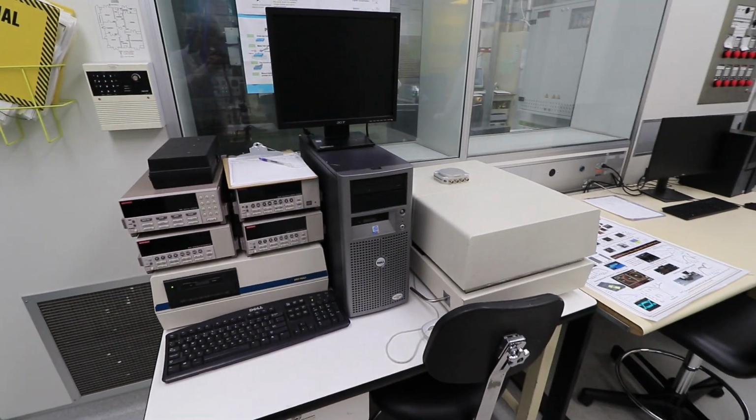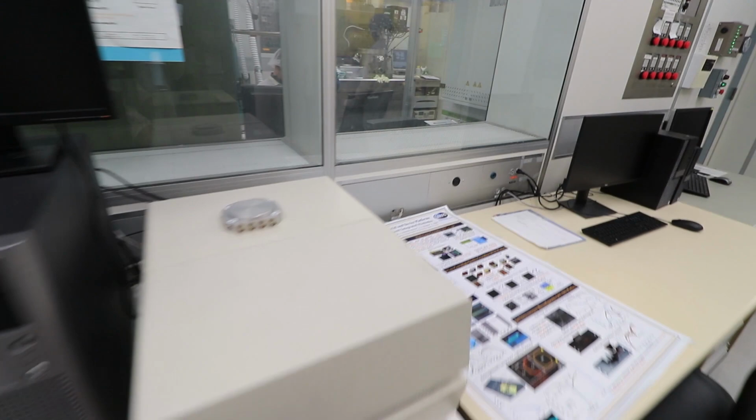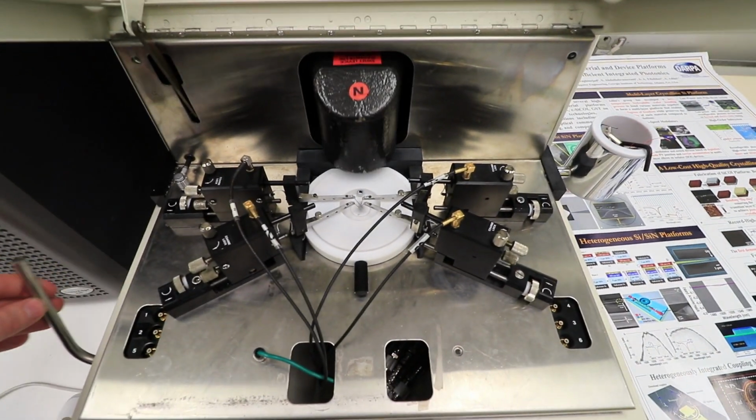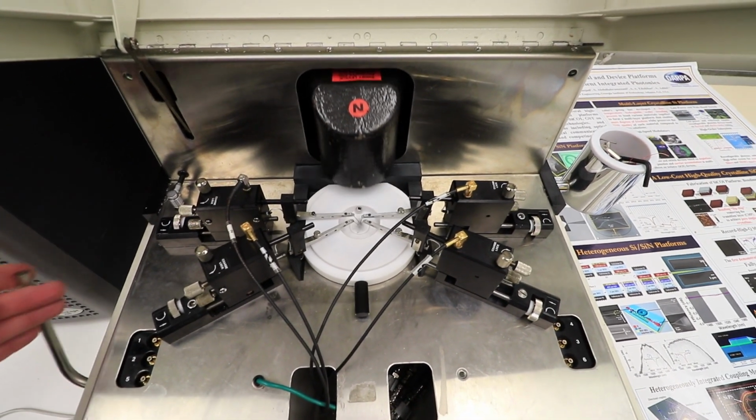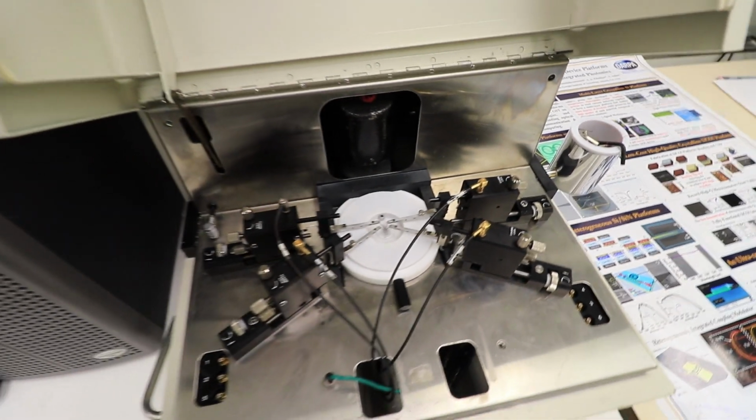Electrical characterizations are also performed using a Hall effect measurement system set up for 4-point van der Pauw measurements with a 0.32 Tesla magnet, a precision current source with a 100 volt compliance voltage, and sensitive electrometers to measure the Hall voltage from even the most resistive samples.